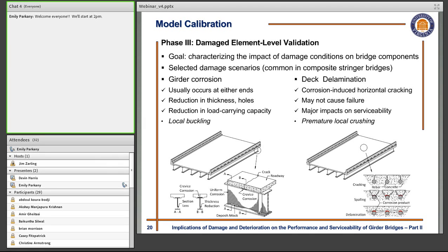And in phase 3, we actually selected two types of damages which are believed to be the most common type of deterioration in these specific type of bridges, the composite steel girder bridges, which are girder corrosion and deck delamination. So girder corrosion usually happens at either end of the structure as a result of leaking from the expansion joint or spraying from the passing vehicle underneath the structure. The corresponding damage mechanism would be a reduction in the thickness of the web plate and bottom flange stiffeners, and this type of damage scenario may cause the structure to reduce its ultimate capacity because of the existence of local failure mechanisms such as local buckling or web crippling or crushing of the end stiffener in the vicinity of the support.